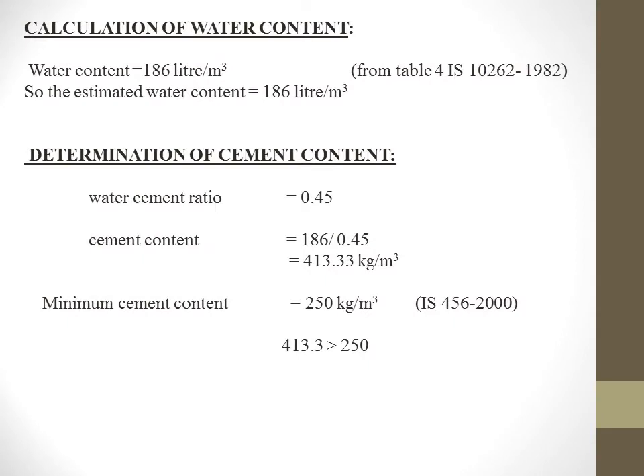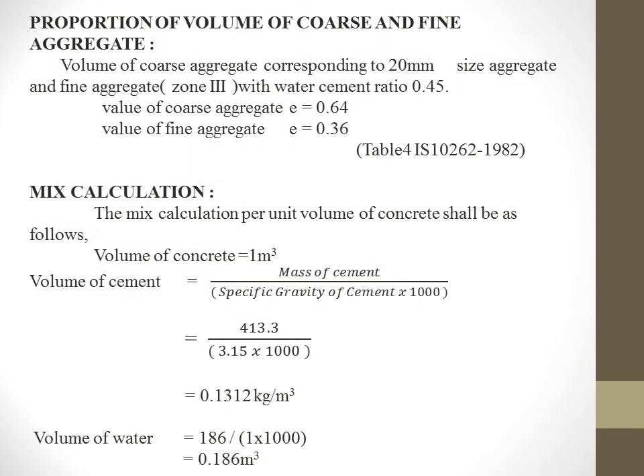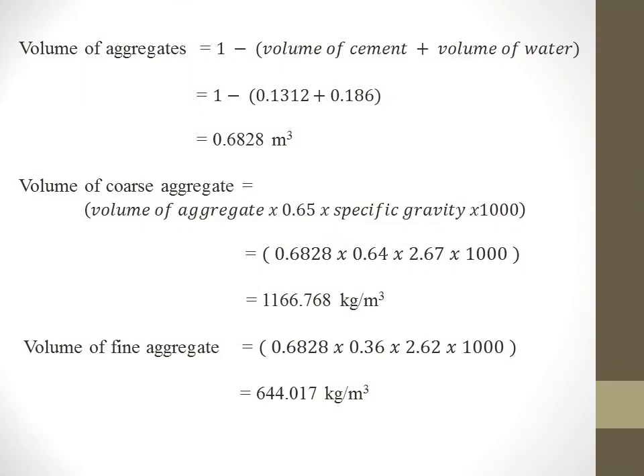Now we had come to the determination of cement content. We had determined the cement content from the water content and the water cement ratio, and the value of cement content was found to be 413.33 kg per meter cube. The volume of coarse aggregate and fine aggregate from Table 4 of IS 10262 1982 was 0.64 and 0.36. So we had put that here, and we had found out the coarse aggregate to be 1166.768 kg per meter cube, and the fine aggregate was 644.017 kg per meter cube.